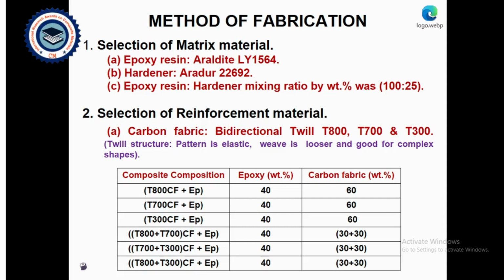Method of fabrication: selection of matrix material. First one, epoxy resin, Araldite LY1564, hardener Aradur 22692, and the epoxy resin to hardener mixing ratio by weight was 100:25. Selection of reinforcement material: carbon fiber will be bidirectional twill T800, T700, T300, and the combinations T800 with T700, T800 with T300, then T700 with T300. Twill structure, why we selected it: the pattern is elastic, the weave is looser and good for complex shapes.